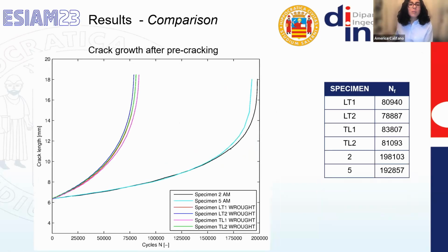In the end, if we compare the results for the 2 sets of specimens, we can see a clear difference in crack growth behavior. This difference has to be found in the fact that the 2 materials have different microstructures, and that the wrought material was in simple annealing conditions, so it was not post-treated. Therefore, we can also see a clear difference in the number of cycles to failure if we compare the 2 sets of tested specimens.